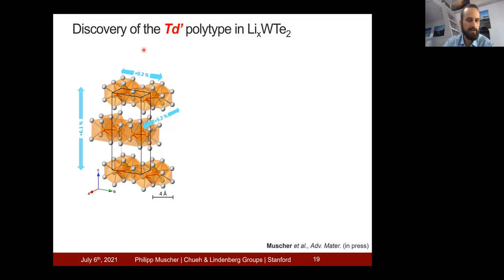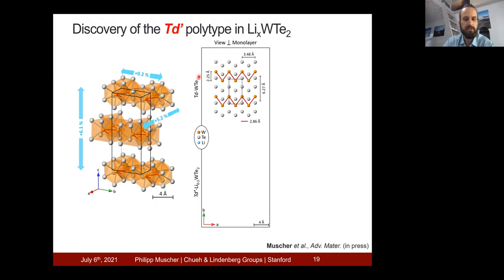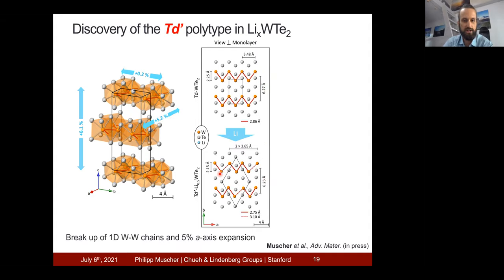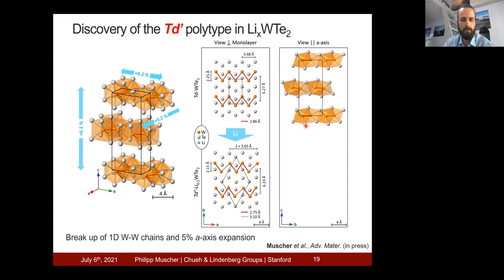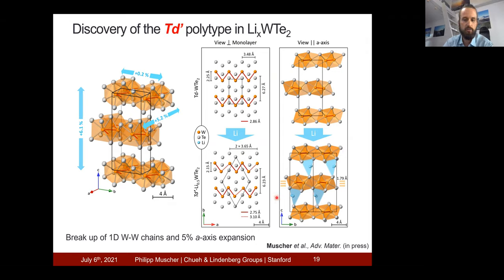So if we look in more detail at just one of these monolayers, let's look from the top at one of those. In the pristine material where no lithium has been inserted, we have these tungsten chains that I mentioned previously. However, after lithium insertion, these chains actually break up into clusters of four. Also, you can see that the material changes from an orthorhombic unit cell to a monoclinic unit cell. We can now also look at the side view of this structure. In the pristine material with no lithium, this is the structure. And after lithium insertion, we see an interlayer slide of the layers. We can also see in this depiction that the lithium ions are sitting in the van der Waals gap in tetrahedral sites.